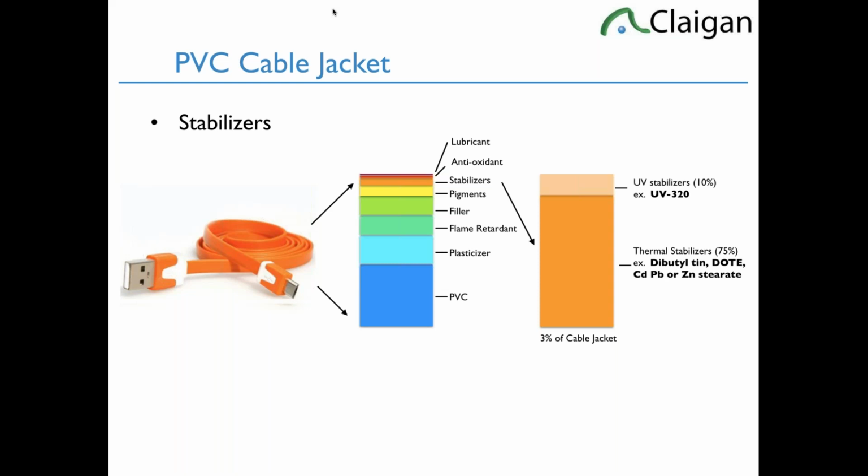And classically, the main stabilizers for PVC were dibasic lead stearate or dibasic lead sulfate, or barium cadmium stearate, stearate being soap, so barium cadmium soap, which are also, if you know your SVHCs, like I'm sure everybody does, SVHCs in and of themselves. So from a RoHS point of view, it doesn't care. The lead is a failure and the cadmium is a failure.